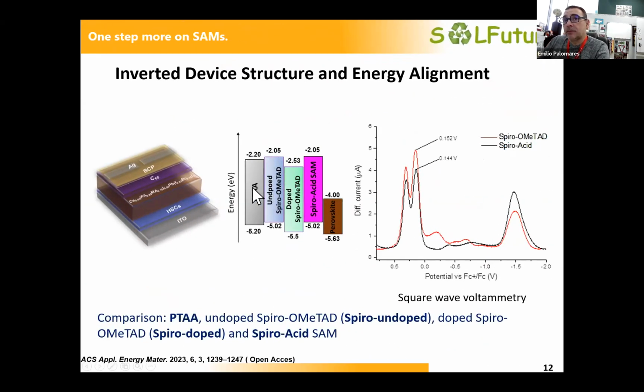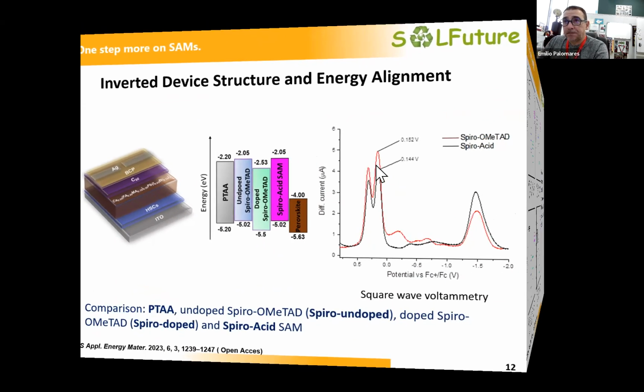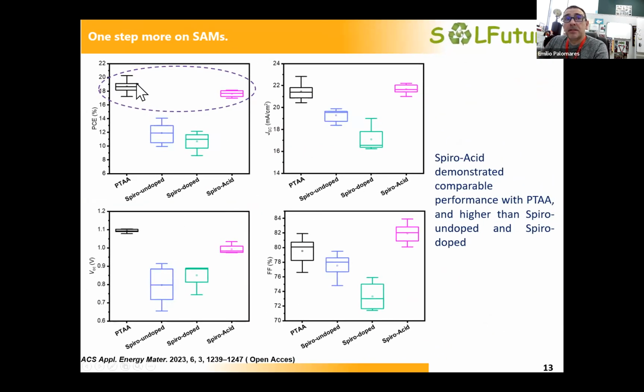So you really have to replace the PTAA or the Spiro-OMeTAD by the SAM. The spiroacid has a little bit shifted the oxidation potential, and that has an effect on the VOC of the cell, as you will see later. But the nice thing is that it becomes much more stable than the films of the Spiro-OMeTAD. Here are some examples of efficiencies of these spiroacids, the SAMs of the Spiro-OMeTAD. So you can reach high efficiencies. This is an average of more than 1,000 devices, and you can reach efficiencies of about 19%.